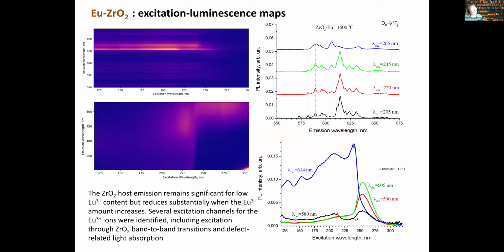And if we check the excitation spectra for this band at 614 nanometers, you see that we have completely different excitation spectra. The blue one is most probably due to band-to-band transition, close to the zirconium band gap. It's about 240, 250 nanometers, and some transitions appear here. And for other bands, we have one broad peak, and it can be either a transition from a charge transfer band from oxygen to europium 3+, or it can also be one type of oxygen defect, like oxygen vacancies, that we cannot separate in this way. However, we can say that if we use band-to-band excitation, that is possible in our case only at DESY for our samples, then we can definitely get emission from rare earth ions via excitation through the host absorption.